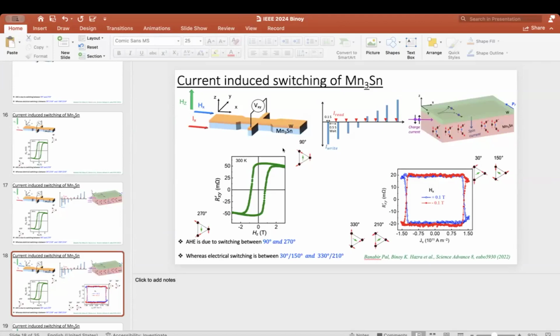So typically in the anomalous Hall effect, the ordinary Hall effect is proportional to the external magnetic field, which is observed in typical non-magnetic metal. And when you have a spontaneous magnetization, let's say iron, nickel, cobalt, or any ferromagnet, then there will be an additional contribution in the transverse resistance. So that will be the external magnetic field plus your spontaneous magnetization contribution. So if magnetization is more, then your Hall resistivity will be more. That is typically the case for ferromagnetic material.